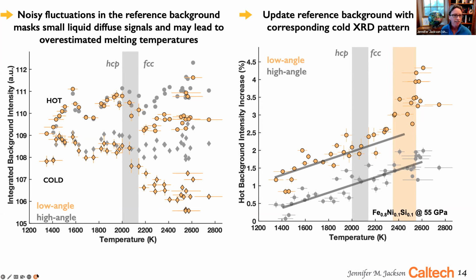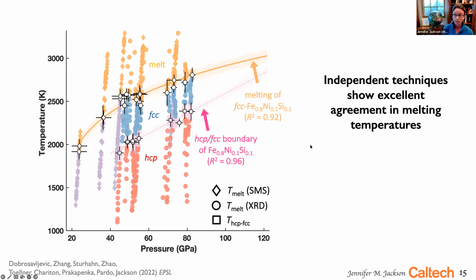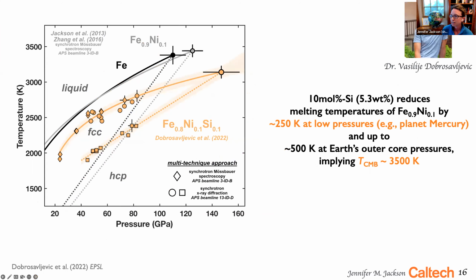Using these two independent techniques, we populate the phase diagram of this iron-nickel-silicon alloy, finding excellent agreement between them. We conclude that 10 mole % silicon, a typical concentration of silicon invoked for the composition of Earth's core, reduces melting temperatures of an iron-nickel alloy by about 250 degrees at relatively low pressures, i.e. the planet Mercury, and up to about 500 Kelvin at Earth's outer core pressures. This would imply a temperature of the core-mantle boundary around 3,500 Kelvin.